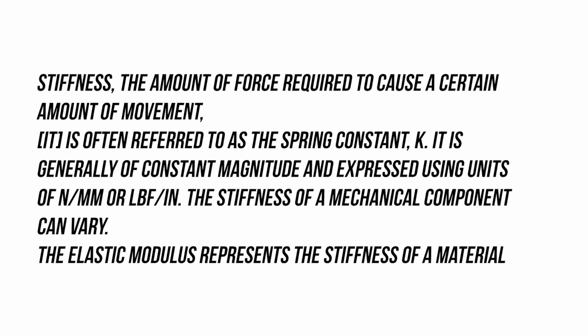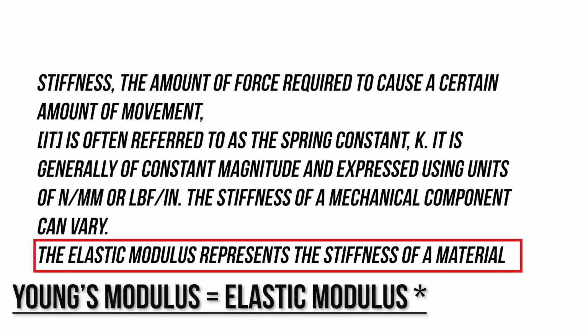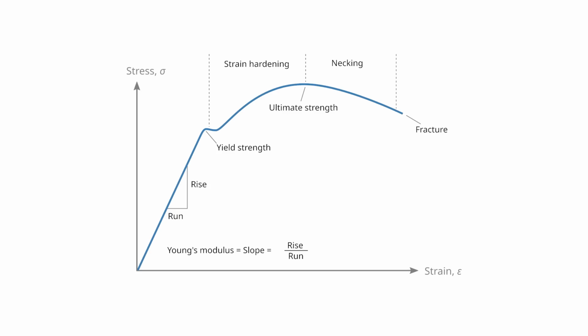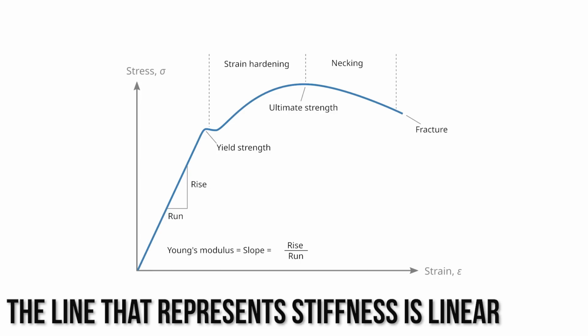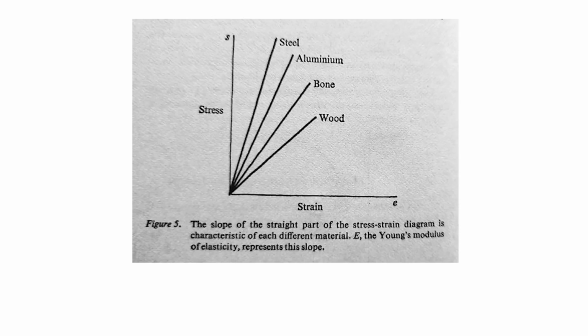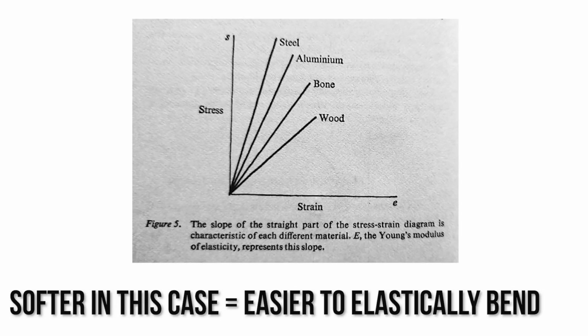Now the way that we generally refer to the stiffness of a material is the modulus of elasticity, or Young's modulus. And what it is is this straight linear line. And what it shows is that the force that you put in is going to be proportional to the amount of strain that you get out. And as you can see, softer materials have a very low angled slope because it takes less force to stretch it a certain amount compared to a more rigid metal. Under the same amount of force, we see less strain.